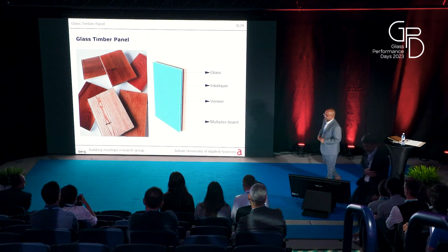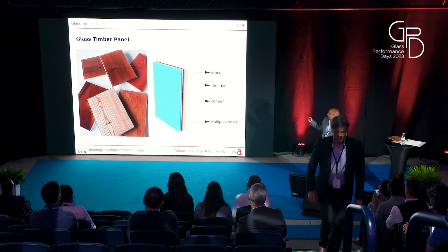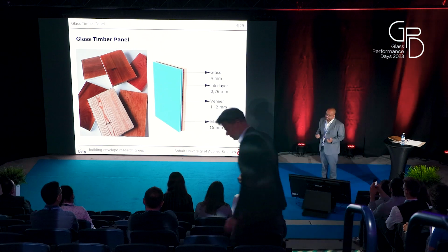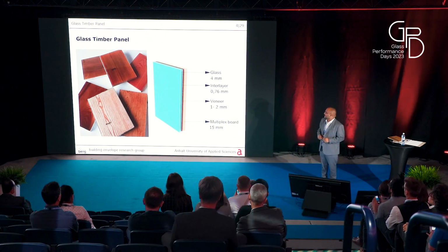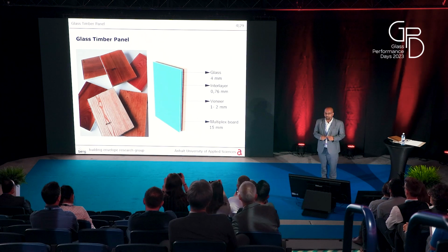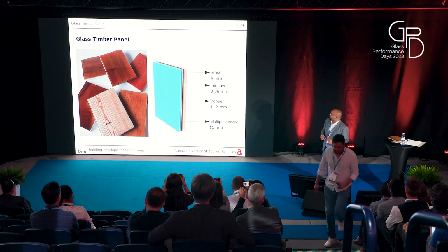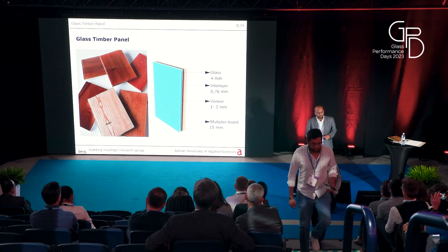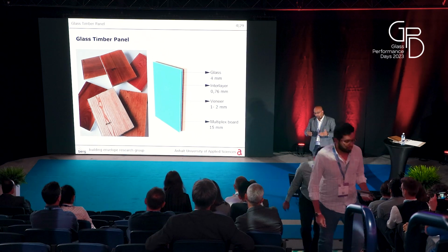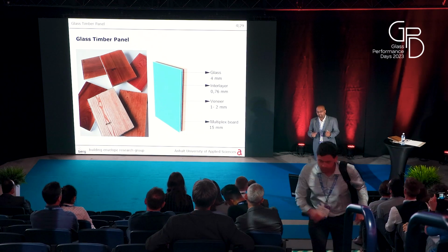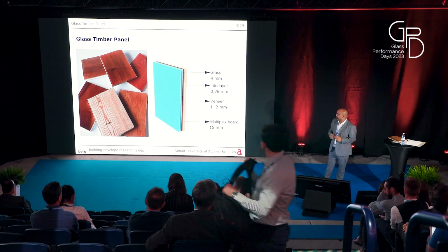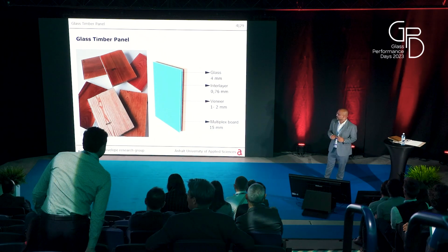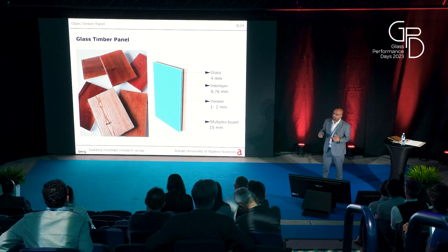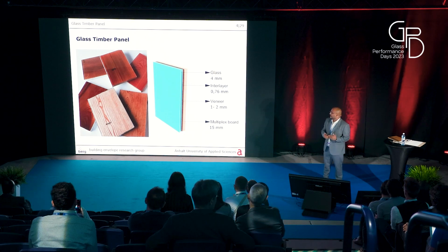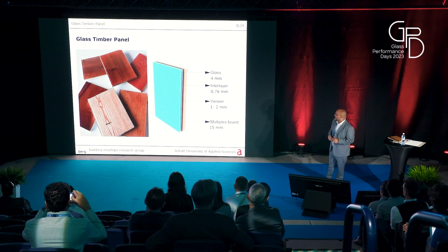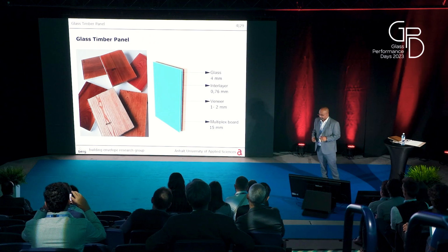We used 4mm annealed glass and an interlayer of 0.76 mm thickness, and we used veneer instead of raw wood, because raw wood has a rougher surface and is hard to laminate. We did some trials, but they didn't work out well. We had a lot of delamination and bubbles. So we used veneer because it's already processed, smooth and easy to laminate, and we used a wooden board in the back.